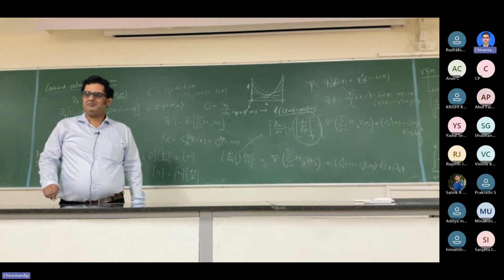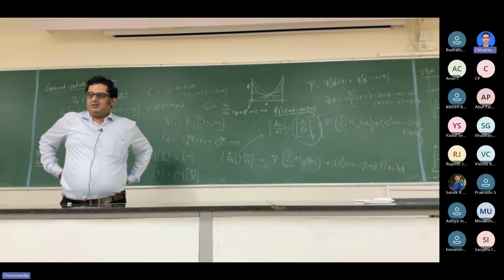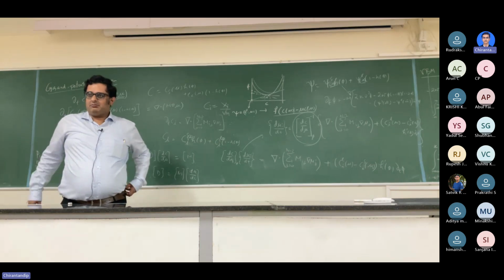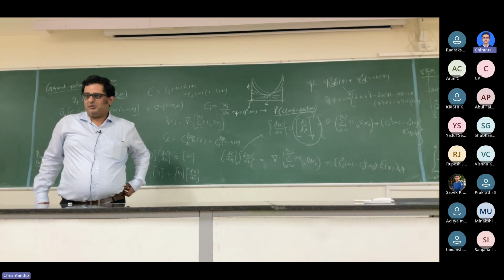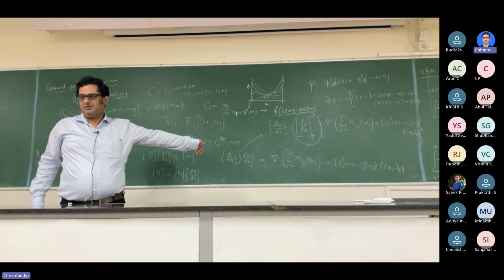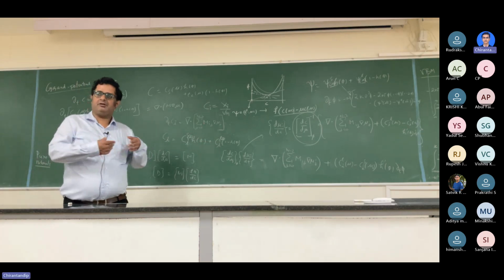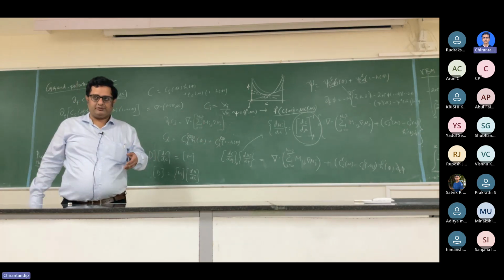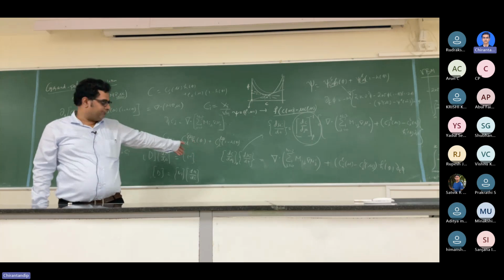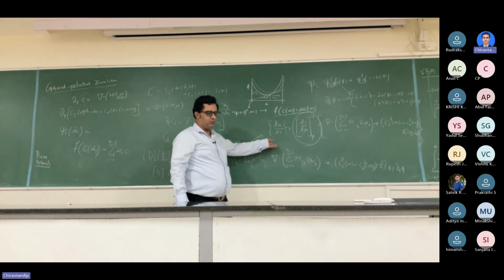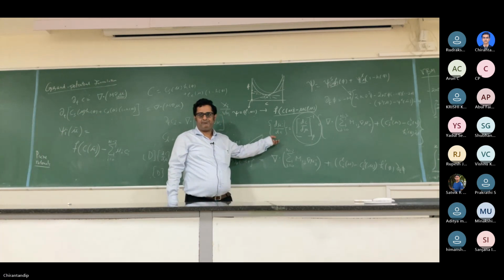Did you compare the computational efficiency? Yes, of course, the case is clear. There's no doubt. For each of those compositions, you typically need 3 to 4 iterations. I mean, at the start you need more, but then you reduce down as time progresses. But typically you need 3 to 4. Whereas in the grand potential, that same composition will be done out of one single operator.